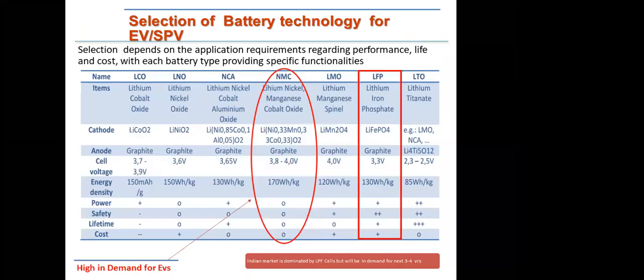Generally, if you see, the market is dominated by these chemistries like lithium cobalt oxide, lithium nickel oxide, lithium nickel cobalt aluminum oxide, or lithium nickel manganese cobalt oxide, NMC, LFP, that is lithium iron phosphate, and lithium titanate. If we see, the market is dominated by these 2 chemistries, NMC and LFP. There is a tough competition between these 2 chemistries, and they have their own advantages and disadvantages.